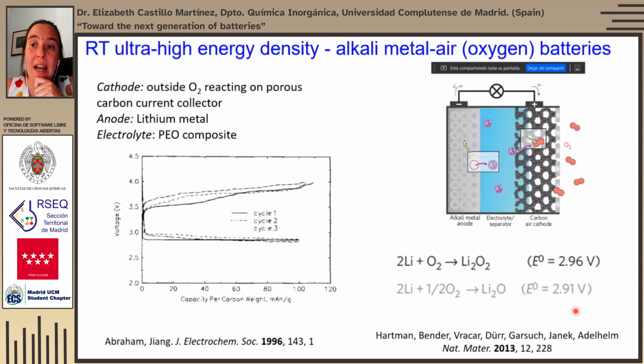On the other hand, the lithium air batteries, which were first shown in 1996 by Professor Abraham, do have an even higher redox voltage, I mean, very close to 3 volts, and similarly high theoretical capacities based on the weight of it. However, if we think that we are taking the oxygen from the atmosphere, we somehow have an infinite theoretical capacity. But actually, lithium in contact with oxygen is forming most of the time lithium peroxide, and this lithium peroxide is a solid that, once in the battery, does contribute to the weight and to the volume of the battery. So the capacity is actually not infinite.